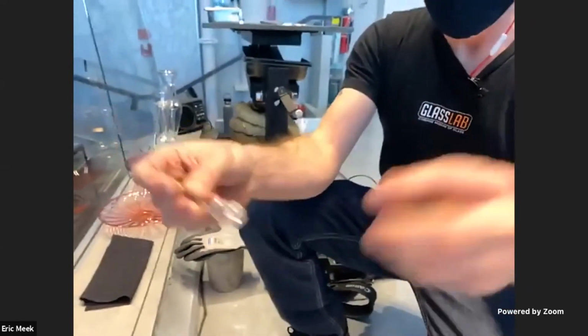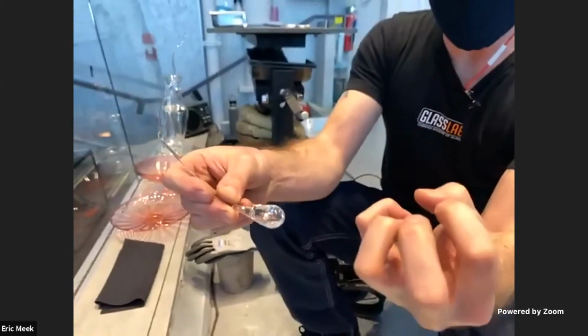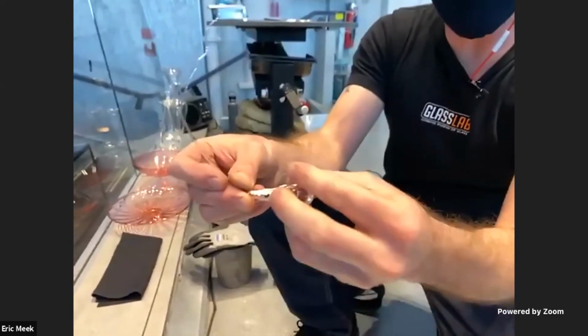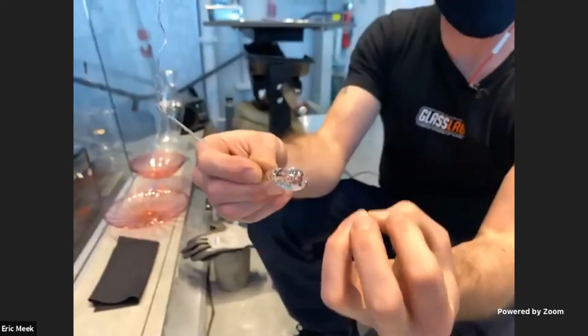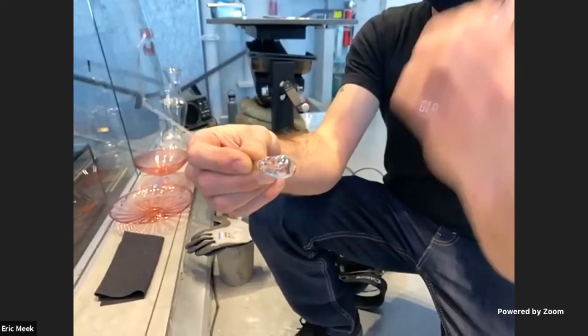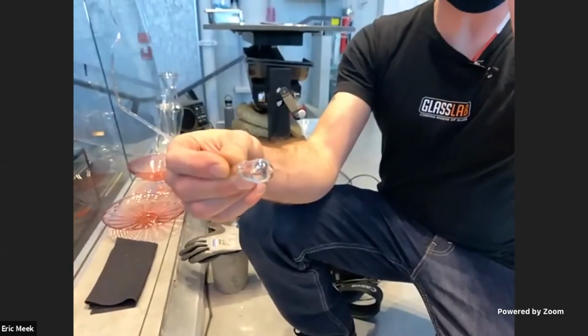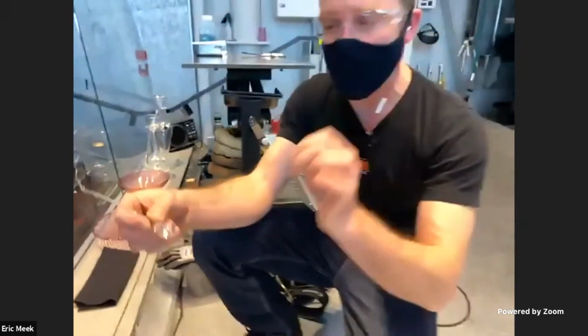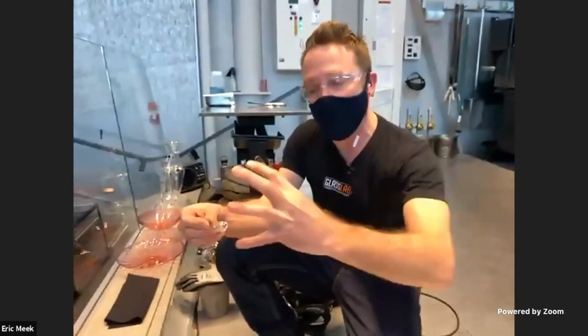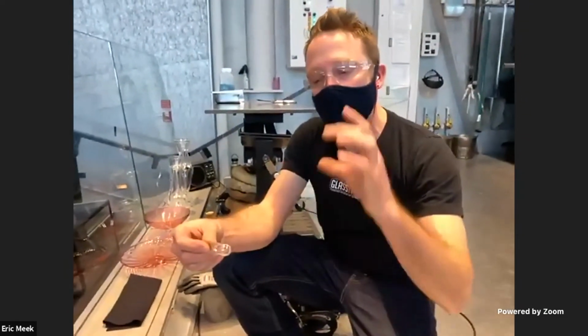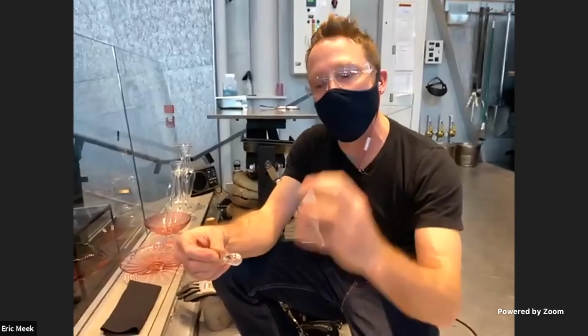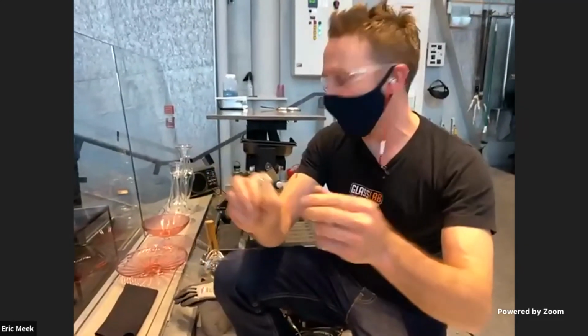So what you get, and we've made a couple of these already, I'm holding on to one. These are called Rupert's drops, Prince Rupert's drops. So the outside gets chilled and it freezes in place almost instantly. The inside, as it's trying to pull in, can't pull the surface in because it's rigid. And what that does is it pulls away from the surface, and that creates tension or tensile stress, which glass under tension is extremely weak. But the compression layer on the outside from cooling so fast creates a lot of durability. Glass under compression is very strong. So this is called the Prince Rupert's drop.